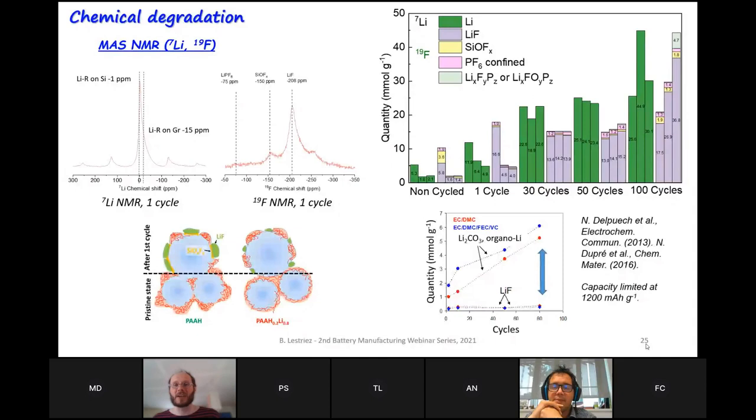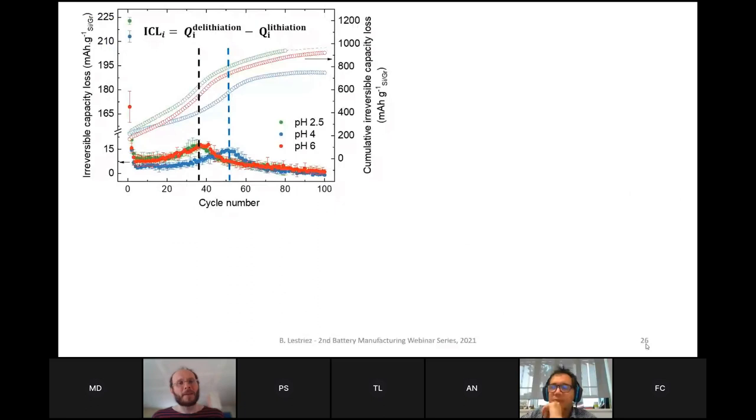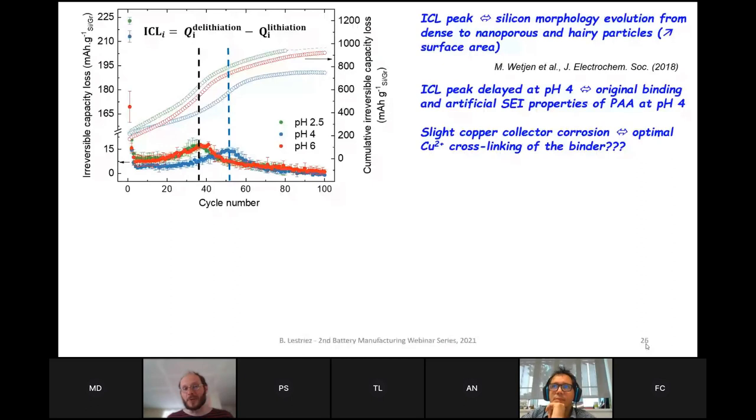Next. So here is finally something which is fairly interesting: to look at the irreversible capacity loss. You have plotted the cumulative values, which are increasing all along cycling, and the instantaneous values that were calculated at each cycle as the difference between the delithiation and the lithiation capacity. So what is obvious is that we have a peak in the irreversible capacity loss curve, which was already pinpointed by Wetjen et al., and they attributed this peak to the irreversible morphological evolution of the silicon particles,